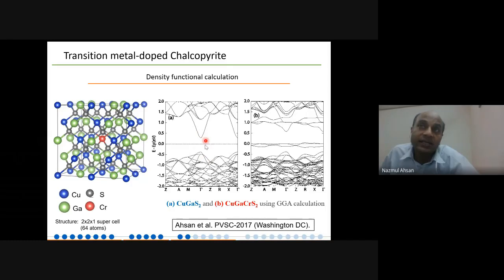And very, very good news is that they have a high absorption coefficient. But now in CGS, you substitute the gallium atom with a little bit of chromium atom. Now the situation changes. In this calculation, suddenly we see new states coming very close to the Fermi level. Zero means the Fermi level. And now the good news is that we have three band gaps. Here we had one band gap, but around the Fermi level we now have three band gaps.